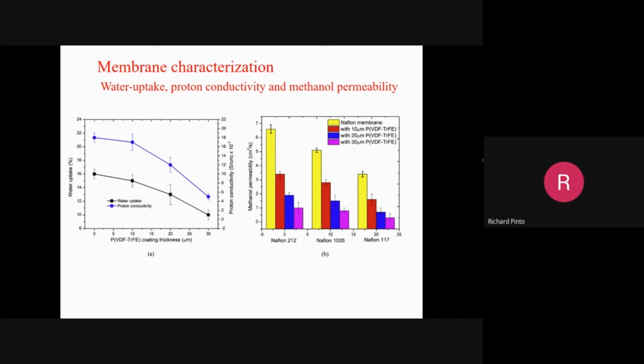But what is the advantage? You see the right side here. Now, different thicknesses of membrane here. We have Nafion 212, which is 50 micron, Nafion 1035, which is 90 micron thick, and Nafion 117, which is 183 micron thick. So this is the status. Normally, we use the 183 micron thick one to reduce the permeability of methanol in the fuel cell into the membrane.